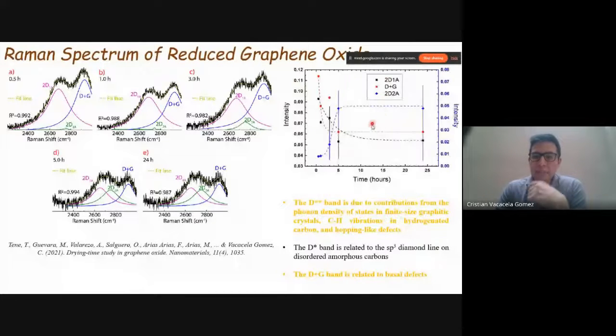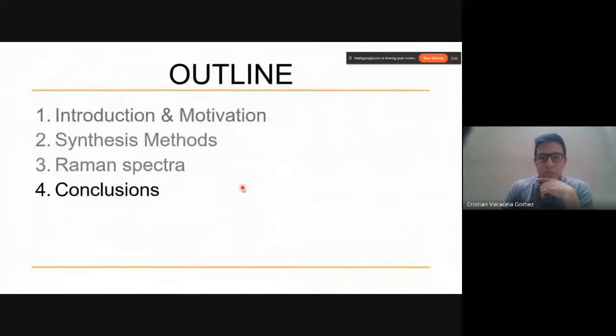Okay, but this result shows that it is not really possible. Maybe, for example, for the 2A, representing this blue color, you can see here is the maximum. Okay, maybe we can increase. So this is a saturation point. Of course, maybe it can be increased a little, but it's not possible to completely reproduce or get the graphite-like structure. But this is the notation for this part, for graphene oxide samples and reduced graphene oxide samples.